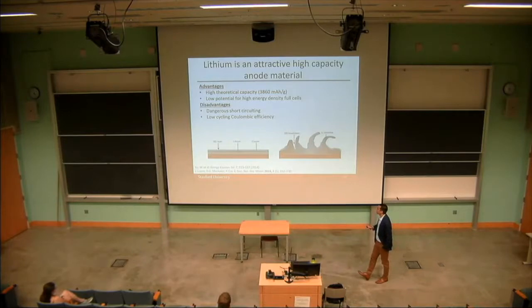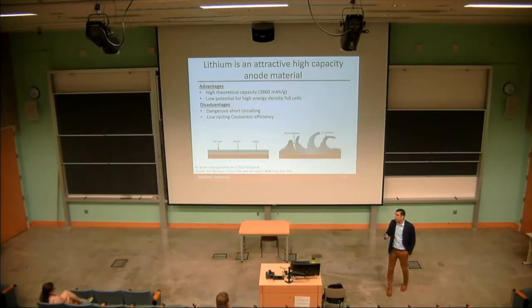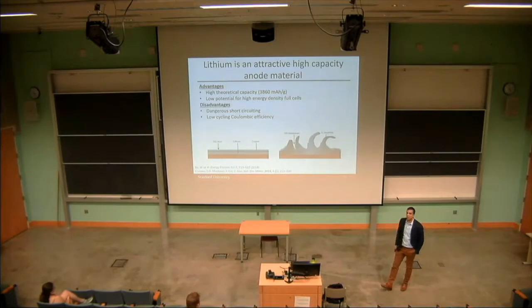Additionally, the lithium metal is highly reactive with all of the chemistries that you put inside the battery. And so any surface of the lithium that's exposed is going to decompose whatever it's in contact with. And you get very high surface area lithium structures in most systems. And so you have very low cycling efficiency because a lot of your lithium and your electrons are going to these side reactions that then limit what lithium you can take back out.